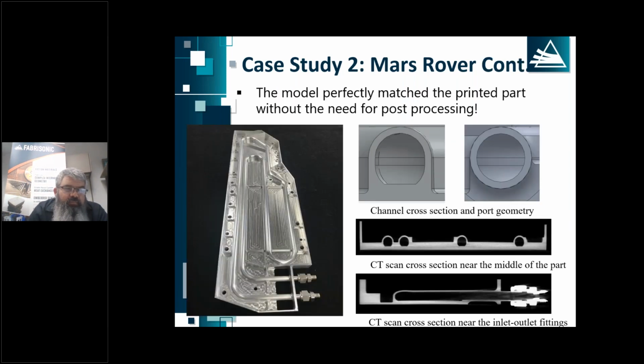Another slide of pictures of that. Again, that part went through quite a bit of testing at NASA JPL. The bottom two images here are some CT scans. And all the CT scans came back clean. Again, pressure tested, helium leak tested, vibration tested, thermally shock tested, and passed all of JPL's requirements.